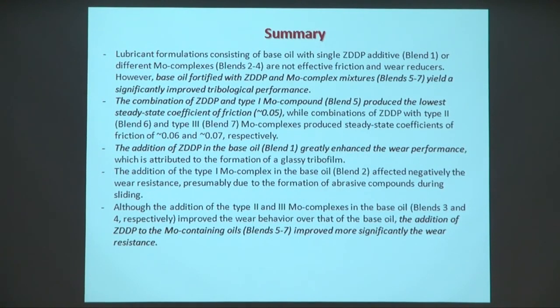So the combination of ZDDP and type 1 molybdenum compound produced the lowest steady-state coefficient of friction of about 0.05. This is very low friction for the boundary lubrication regime. And also the incorporation of ZDDP into the base oil generally enhanced the wear performance, but we know that this is not what we want to see. We want to replace this. And this was accomplished by including these molybdenum-containing oils that improve significantly the wear resistance by replacing the phosphorus and sulfur elements that are present in the ZDDP.